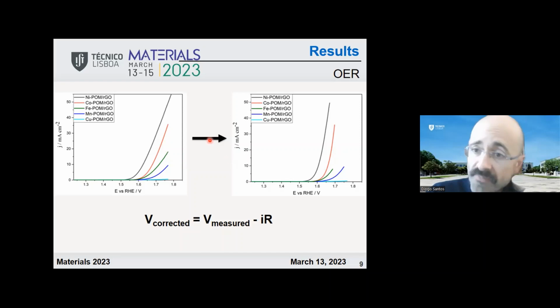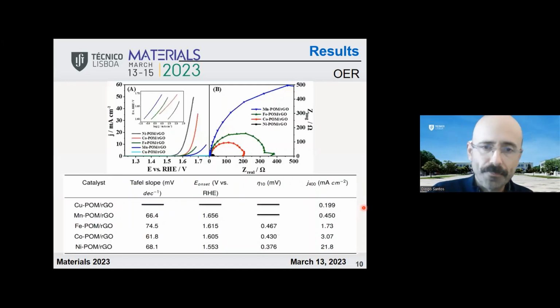We did not only the direct polarization curves, but also the ohmic drop corrected polarization curves, because when you do electrochemical experiments, there's always a small distance between the working and the reference electrode, and you have to deduct that ohmic drop so that you can have more accurate data for extraction of the kinetic data. So you have a more accurate analysis of the produced data.